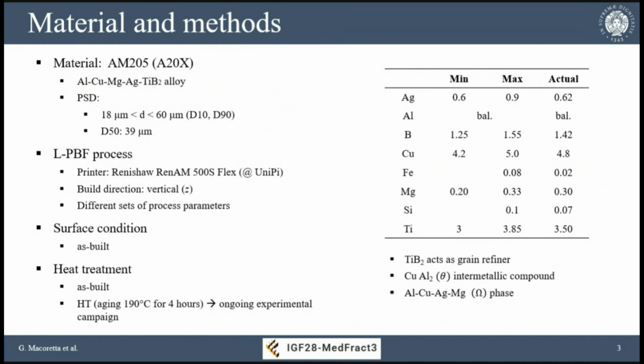This allows us to use this powder for a very wide feasibility region because we can explore different process parameters, paying attention only to the quality of the material in terms of density and pores, standard defects introduced by the L-PBF process, but not dealing with the need of avoiding hot cracks because it's a material with a very low tendency to produce hot cracks.